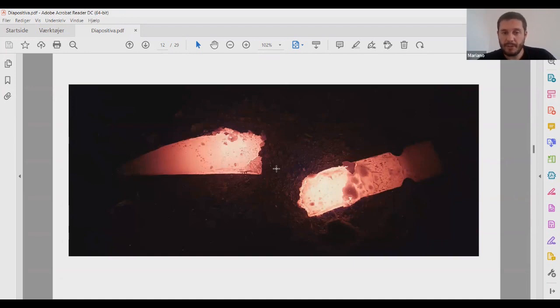Keep in mind the forging temperature and always follow the data sheet of the material you have, because different steels have different forging temperatures. Even if they have the same amount of carbon, for example, you can have this with stainless steel. Normally, stainless steel for making tools is like 1.2 carbon, but for example, for the heat treating it is like 1000 degrees, and normally it is close to 800 if you have a carbon steel.